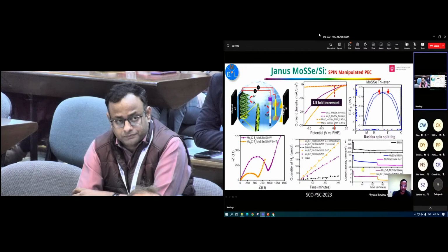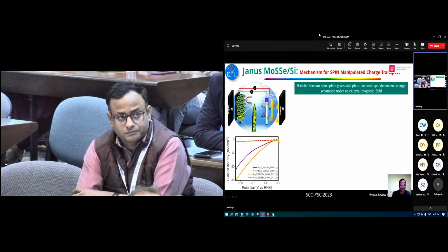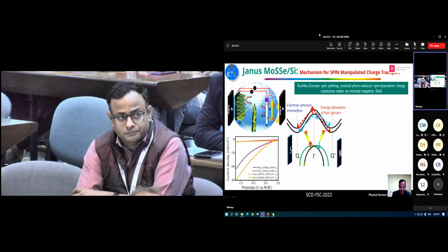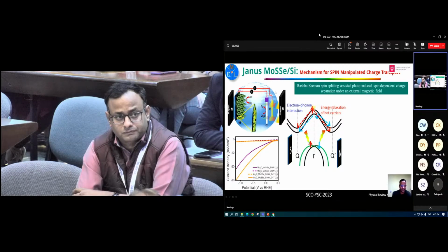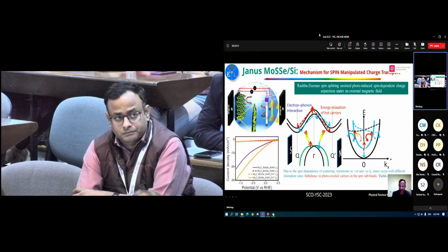Though due to limited time I am not presenting them here, we tried to understand the mechanism. The mechanism is like this: you have Rashba splitting in your valence band and Zeeman splitting in your conduction band. What happens once you excite with a photon is that your electron goes from the valence band to the conduction band as a hot electron, and it relaxes with a phonon. And this relaxation under the magnetic field is spin dependent. So at the end you have a different probability of relaxation in this direction and this direction. So you get asymmetry in the relaxation, and that is where you have an asymmetry in spin electron density.